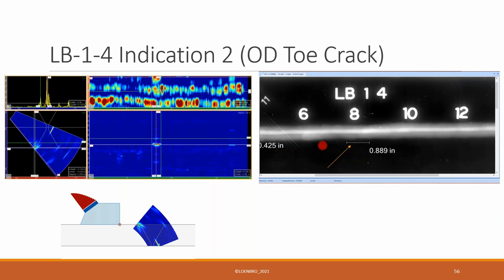And I'm not going to go through all of these. So radiography will hit some cracks. Again, it depends on where the source of radiation is. This must have been more direct over. If the source would have been, say, centered up over here, you probably wouldn't have seen it. So I'm not saying radiography can't see cracks and it can't see lack of fusion. That's just the weakness. It depends on, again, source placement. This is the strength of phased-array. Very high, easily seen signal. And this is at a reference level dB. And again, it's right on the toe of that weld there.